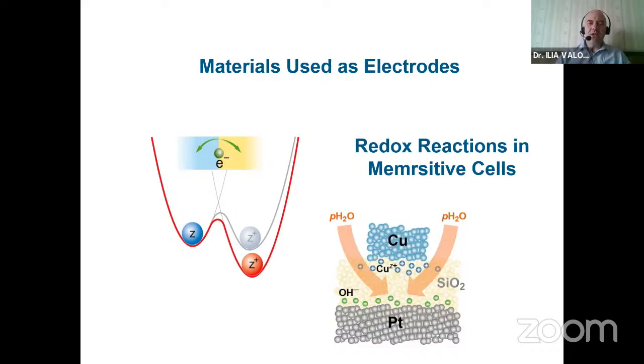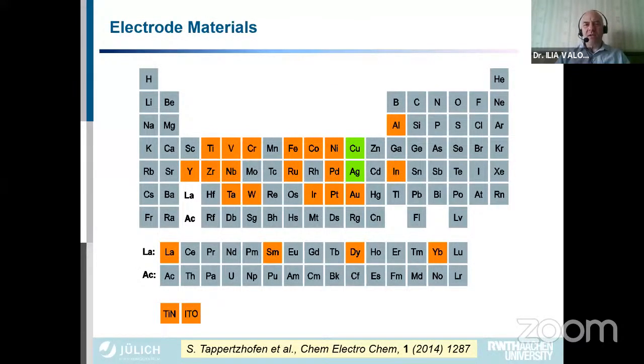Now I'm coming to the materials and what is their role in designing artificial synapses. Electrode materials, or especially active electrode materials, are used very largely in many different materials. So you can see all these colored metal elements are used as electrodes. Of course, mainly popular in the electrochemical metallization cells, or CBRAMs, are copper and silver, but many others are used. And for the other cells, you have many different materials. In fact, the choice of particular metal is only limited by its properties, so how electrochemically active it is, and how fast the ions can diffuse within the matrix, the electrolyte matrix.